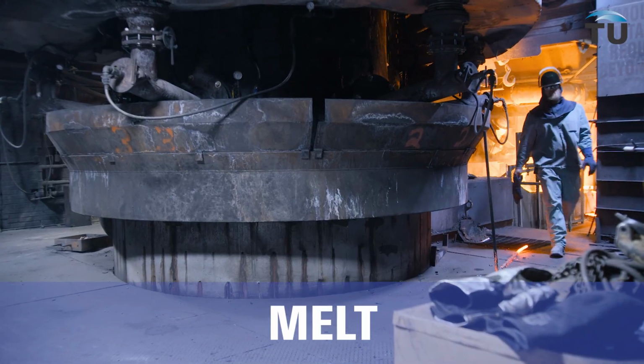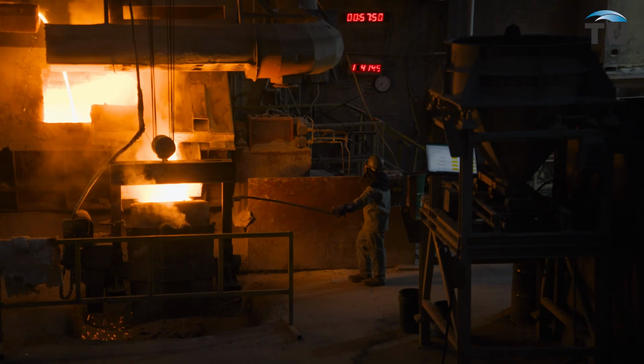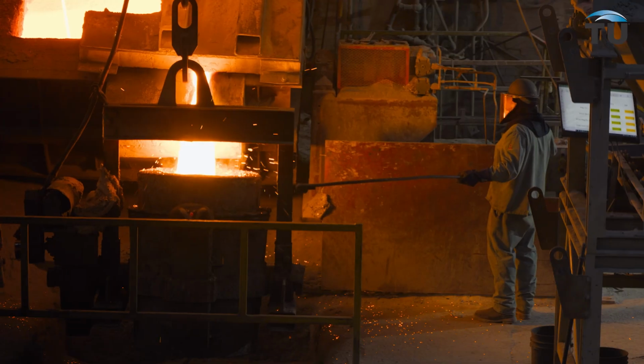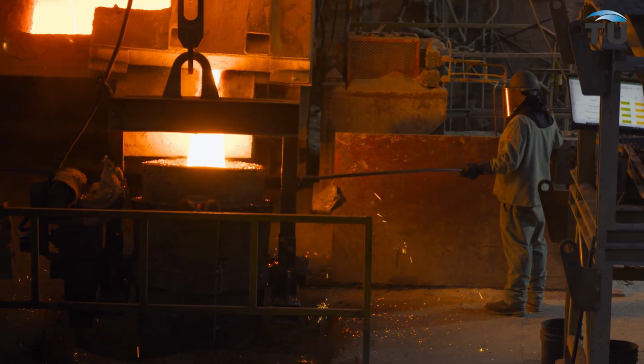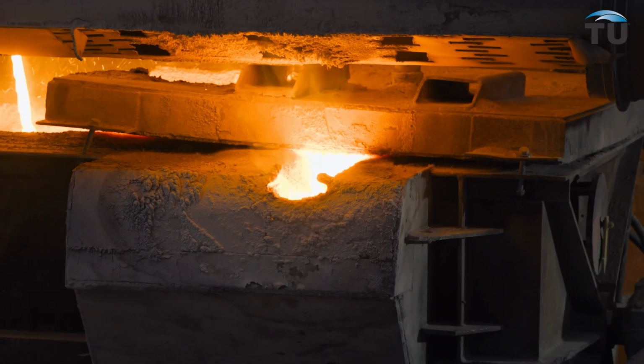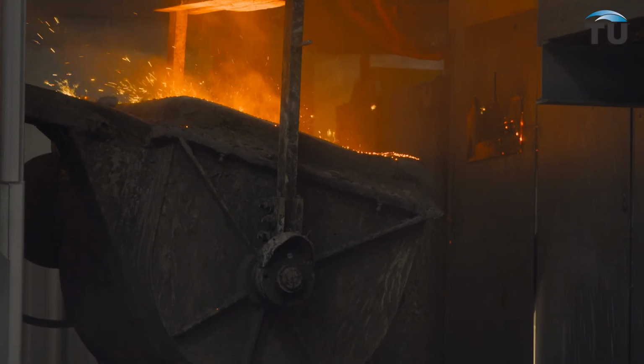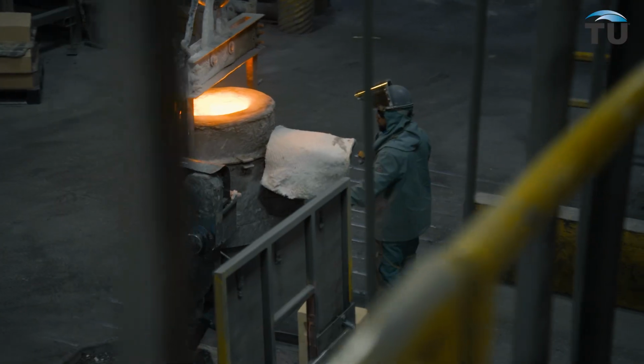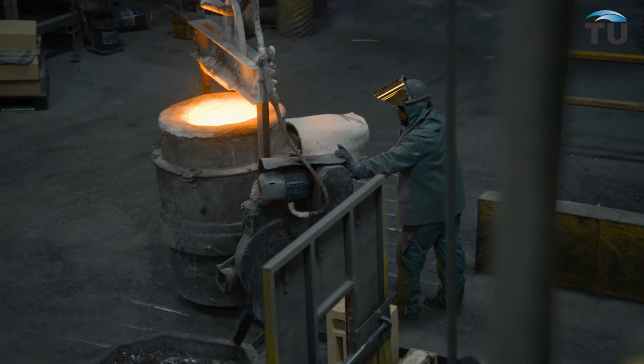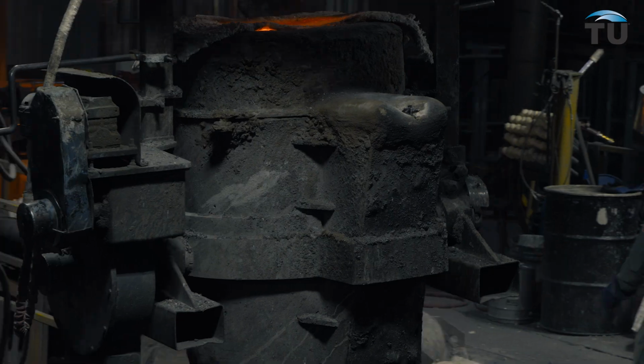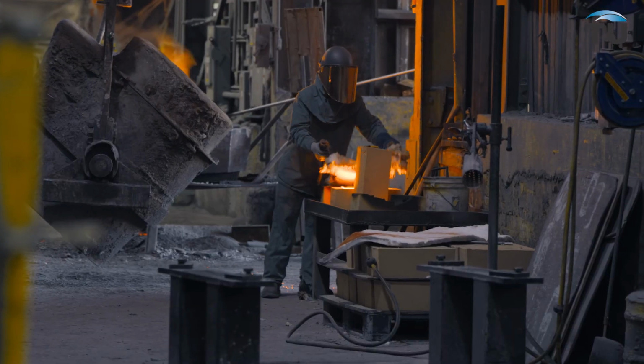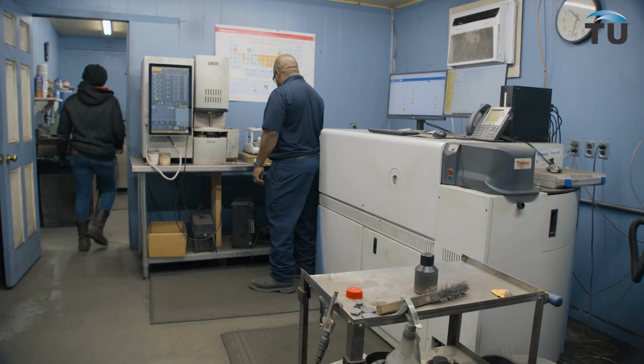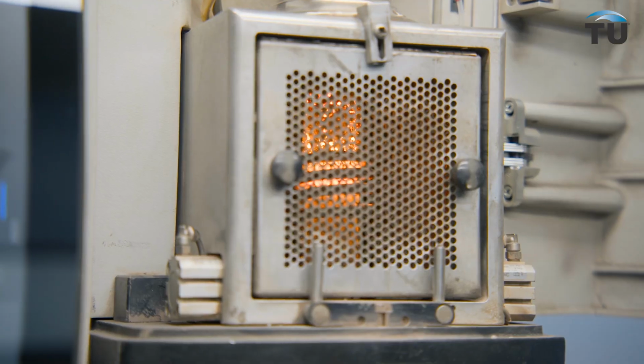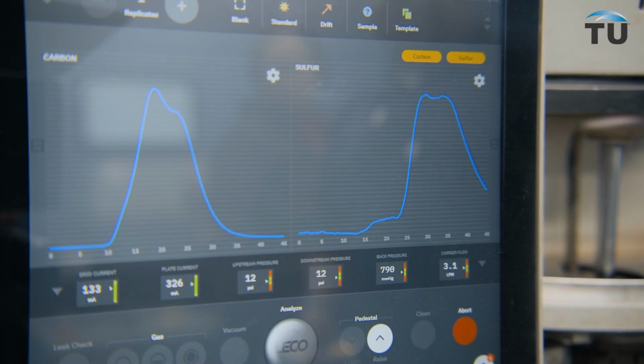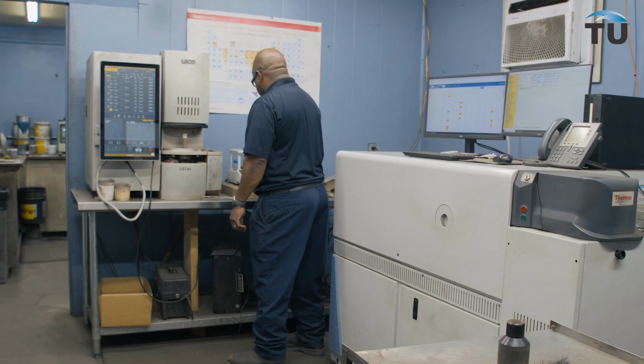In the cupola, ingredients are charged in specific amounts to comply with AWWA standards. We mix scrap iron, foundry coke, and alloys into a charge of metal. This is heated using heated air and oxygen to produce molten iron. The iron goes through a desulfurization process and is then treated in a transport ladle with magnesium and alloys to create ductile iron. Samples of each treated ladle are taken and transported to the iron testing lab. The samples are ground and burned, and a report showing the percentage of each element in the iron is reviewed to ensure quality specifications are met.